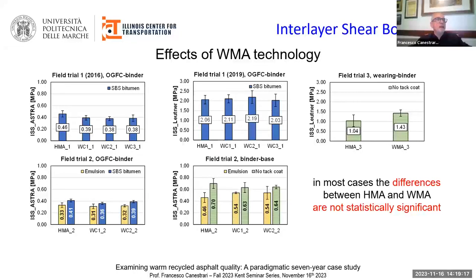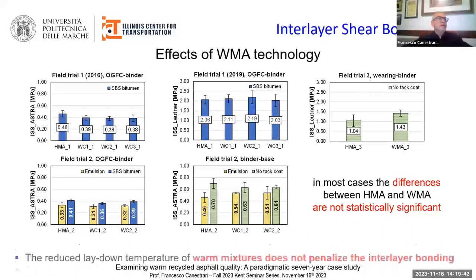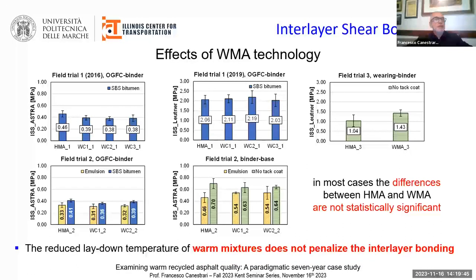In this slide, we can see the summary of the interlayer shear strength results related to hot and warm laydown of the asphalt layers during the construction activities. Whatever the interface considered, there isn't a clear trend because in most cases, the differences between HMA and warm mix asphalt are not statistically significant. Therefore, it can be concluded that the reduced laydown temperature of warm mixtures does not penalize the interlayer bonding of pavement interfaces.